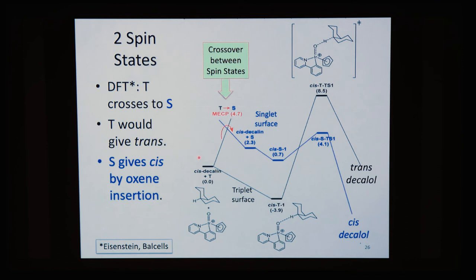Now, very interestingly, Odile finds that the ground state of the oxo is a triplet. And if we follow the triplet surface, the black, and pass over this transition state, we make the wrong product, the trans-decalol. On the other hand, if we have a crossing point between the triplet and the singlet, which occurs at 5 kilocalories above the ground state, then we can pass along the blue curve and we can make the correct product, the cis-decalol. So this oxene-like insertion is caused by a spin crossover between the states.